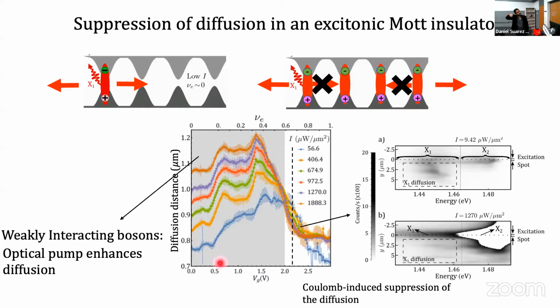But then this limit is interesting because there is a threshold after which this trend inverts. So now higher pumping power leads to lower diffusion in the material. And then this is benchmarking the formation of Mott insulating states.